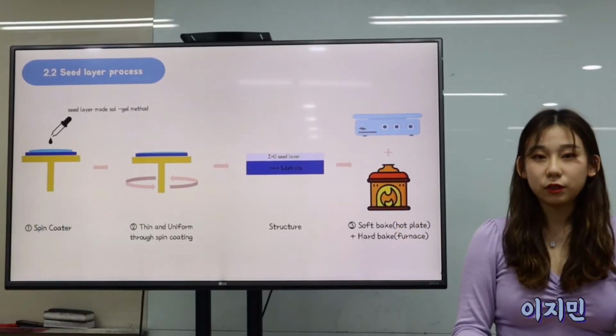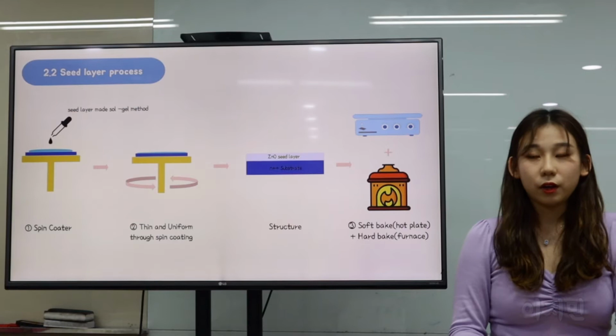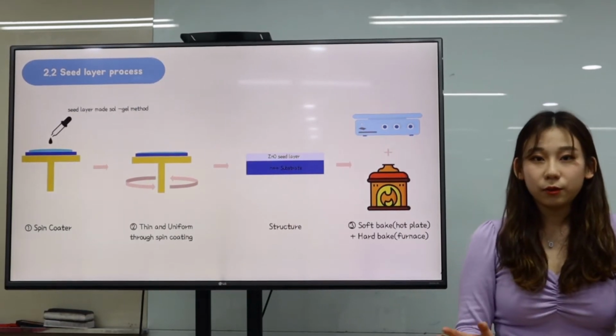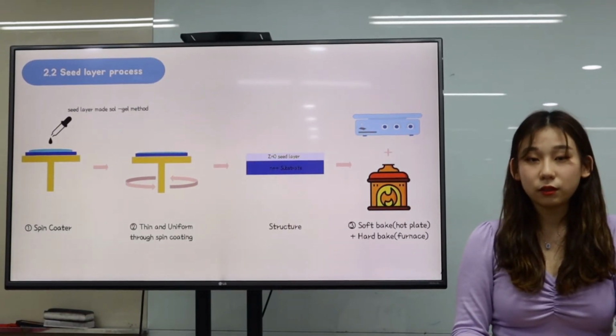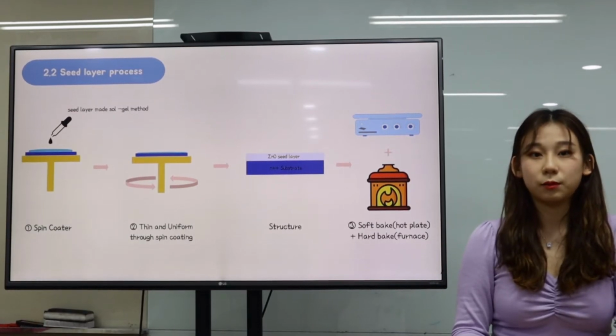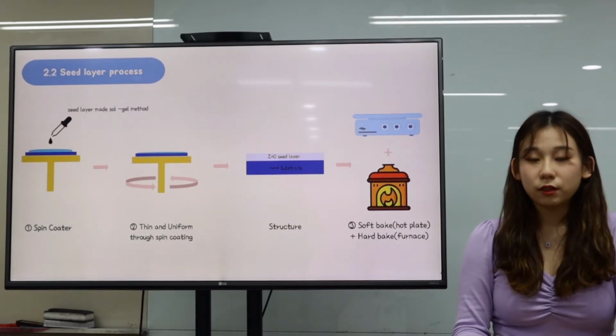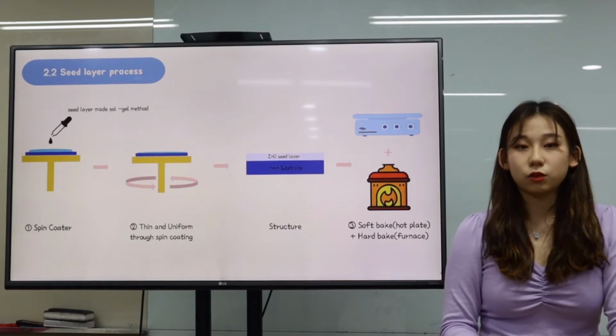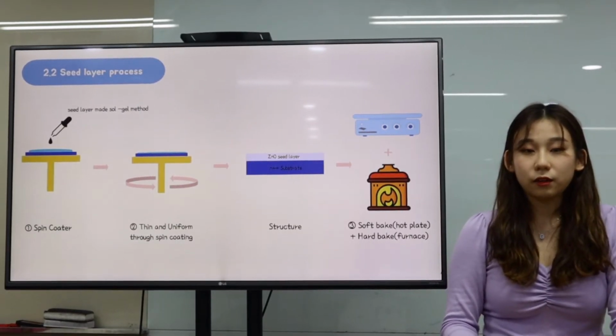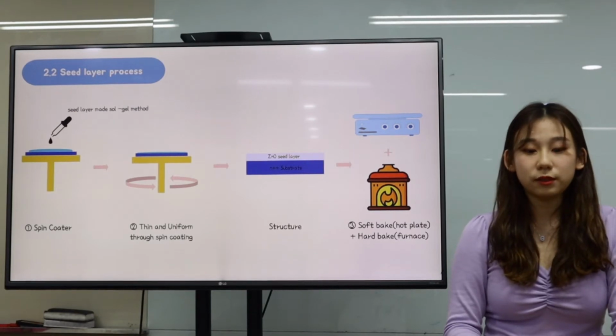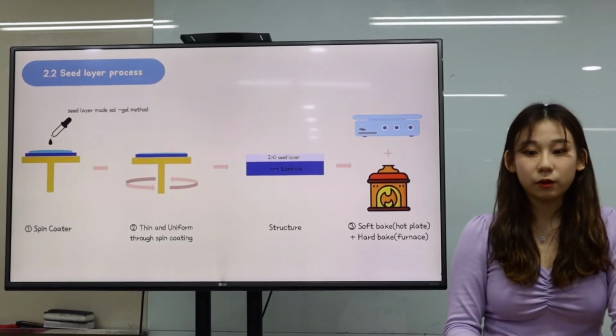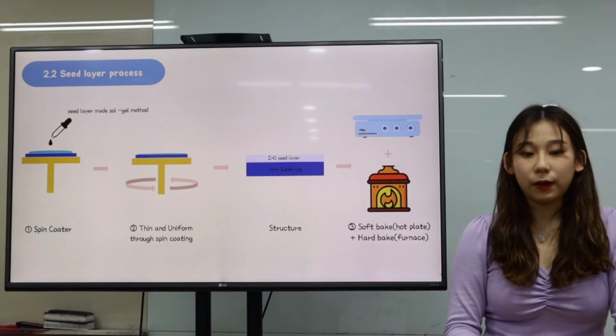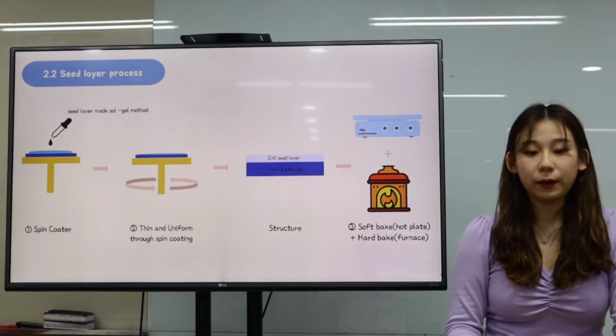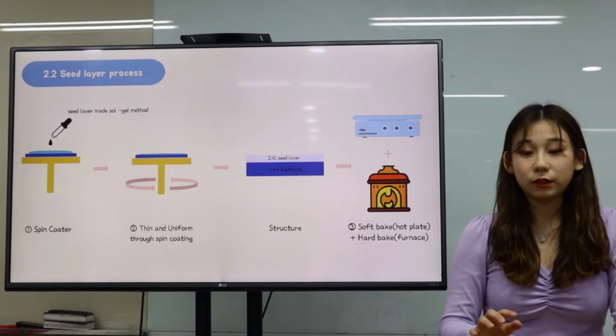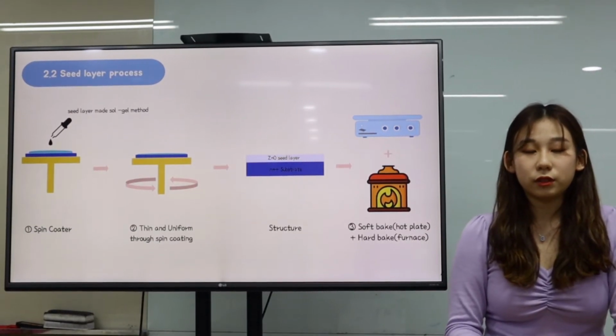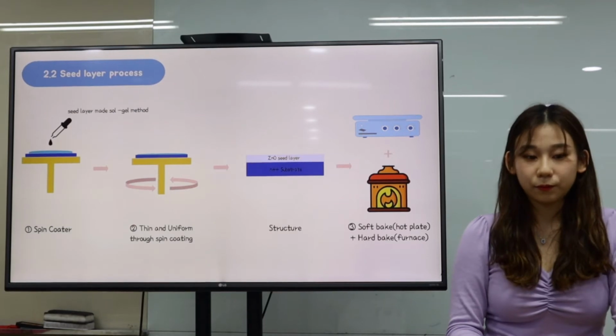Hi, I'm Jimin. I will talk about the research method. Number 1, seed layer process. First, we make seed layer solution by sol-gel and spin coat it on the substrate. Second, spin coat the seed solution to deposit uniformly and thinly. Third, to make the sample crystallinity much better, we do soft bake and hard bake. If the hard bake temperature isn't high enough, the crystallinity doesn't grow well.